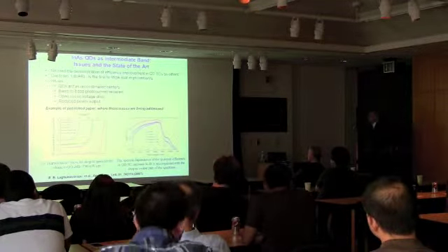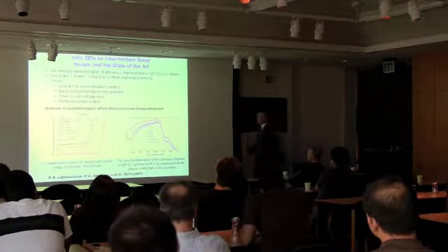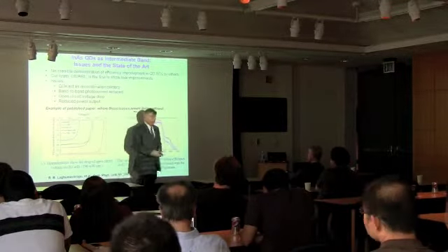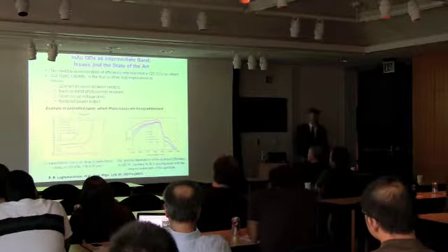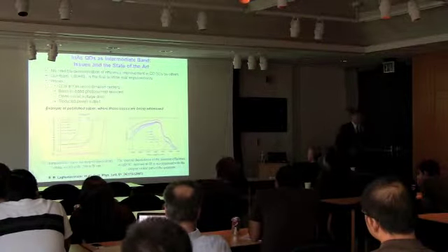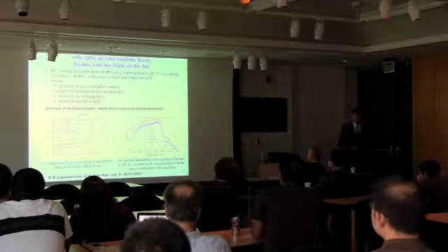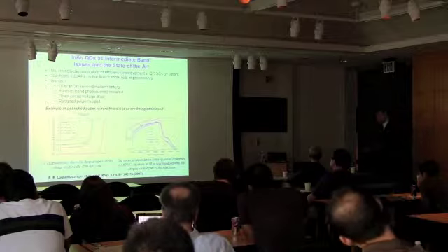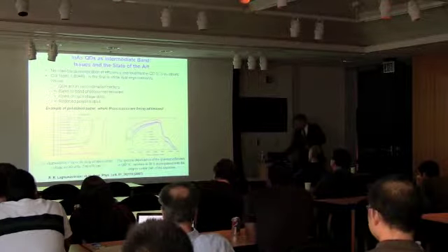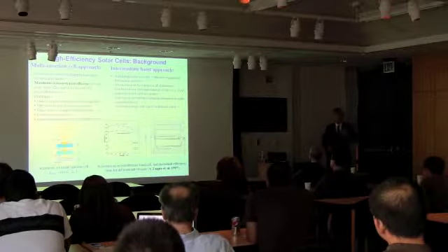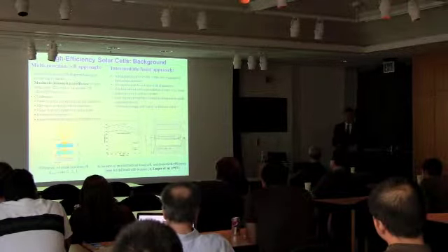But now what happened, if you look into the performance, then the performance went down. You have smaller current and smaller voltages. In some best efforts, the current will be the same or close, and I will show our initial results. The voltage deteriorates. The problem was that in this perfect design, people did not pay attention that, yes, you create additional absorption of the light.